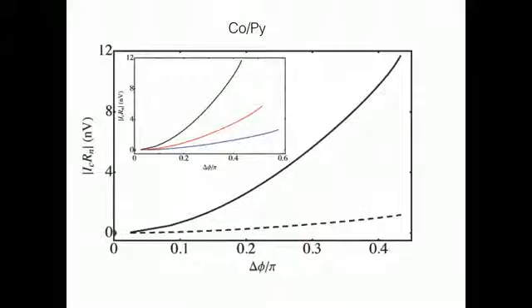The appearance of the current is attributable to the long-range triplet component that increases with increasing twist of the domain wall.